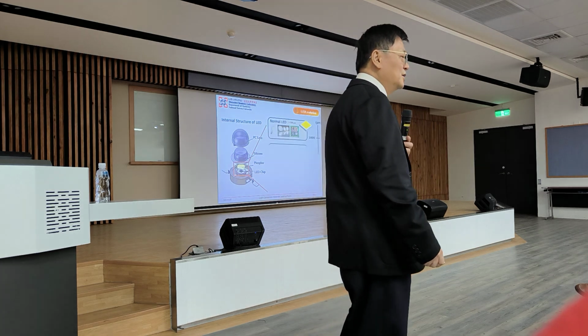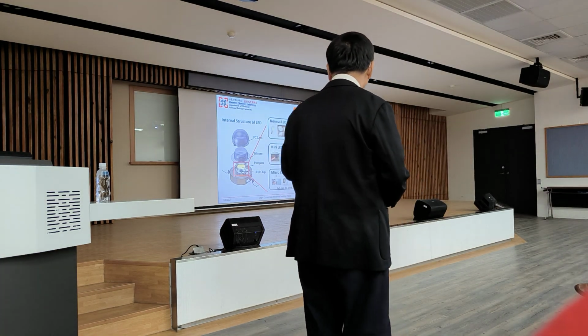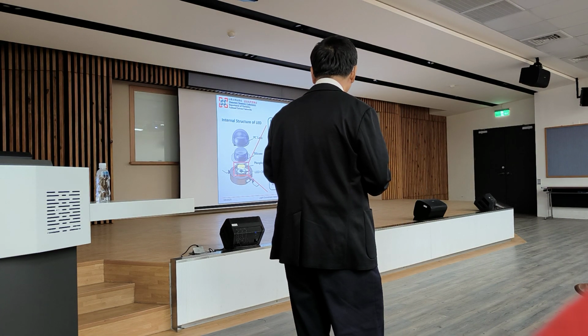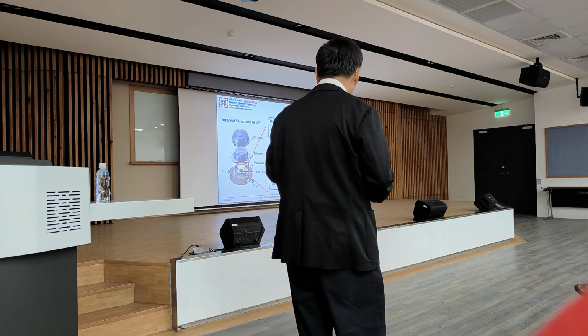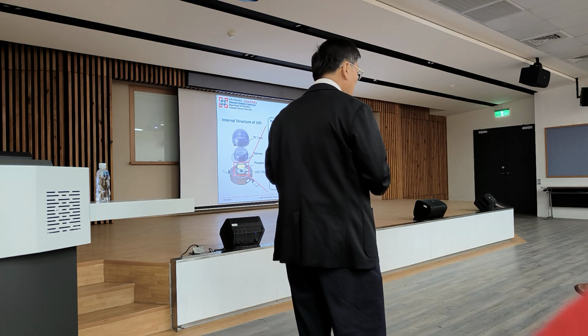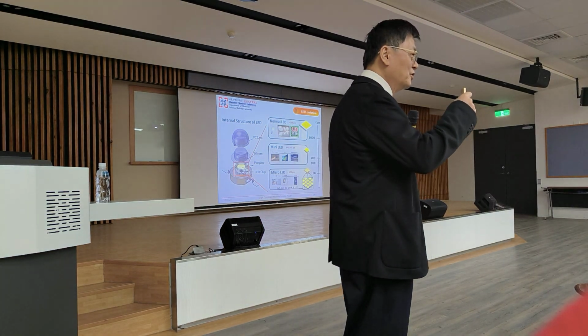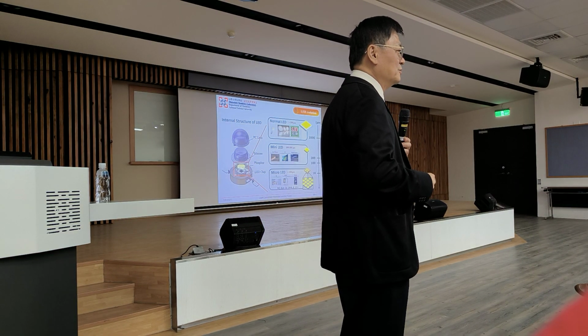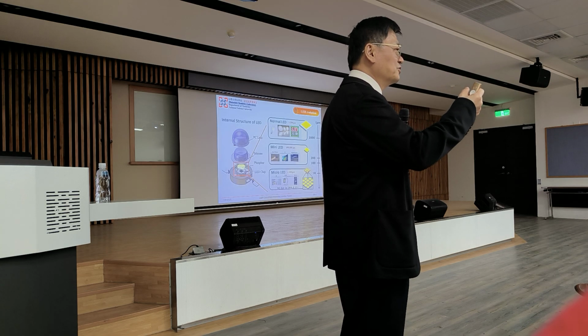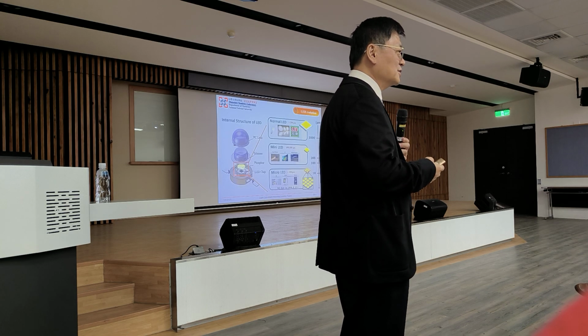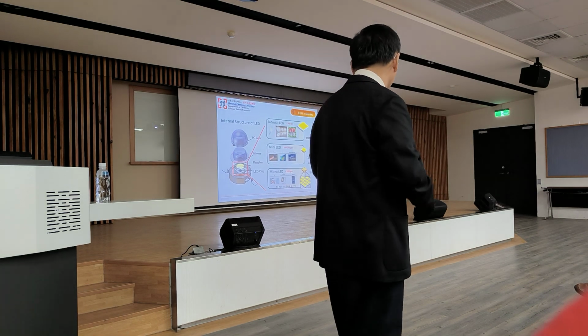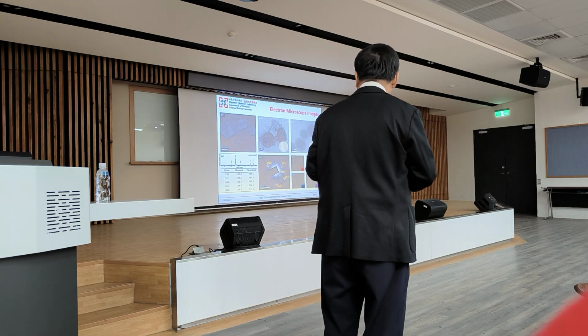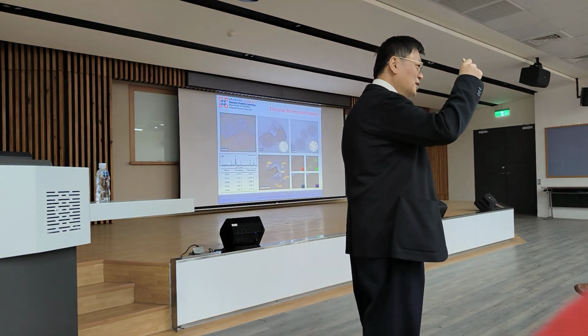And then you can see the scale. So now the LED comes from the normal size, one chip more than 200 micrometers. If we go down to mini, down to micro, less than 100, can you have an infrared phosphor to do it? Because normally, the phosphor size is more than 100 micrometers. How can we shrink the size? Then again, it's a synthesis technology.